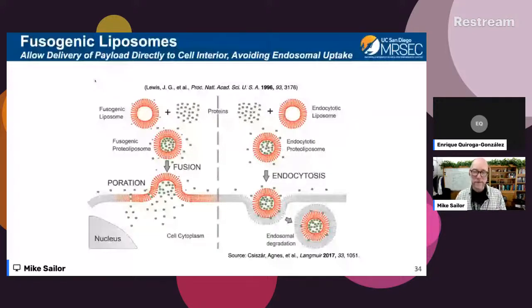When lipids hit cell surfaces, they do one of two things. They typically do what's called endocytosis, what's shown on the right-hand side of the slide. That nanoparticle hits the cell surface and it basically gets enveloped by the cell membrane and taken up into the interior of the cell. But there are some formulations of lipids, if you do it right, that when they hit the cell surface, instead of getting taken up by endocytosis, fuse with the cell membrane, so-called fusogenic lipids. It basically becomes part of the outer membrane of the cell. And so whatever payload is sitting inside that lipid ends up getting dumped directly into the cytosol.